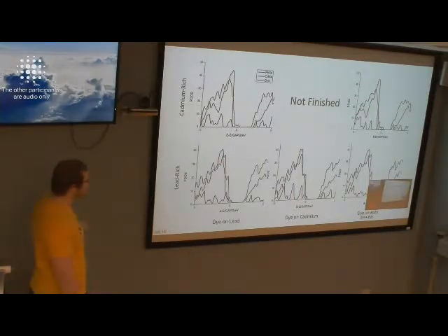So a thing that's quite evident is all the band gaps are closed. And this concerned Jabed and me, and you, I suppose. I didn't actually put it on here, but I calculated one of these structures, I think it's the lead-rich one, with dye on both in acetonitrile, and the band gap was still closed.